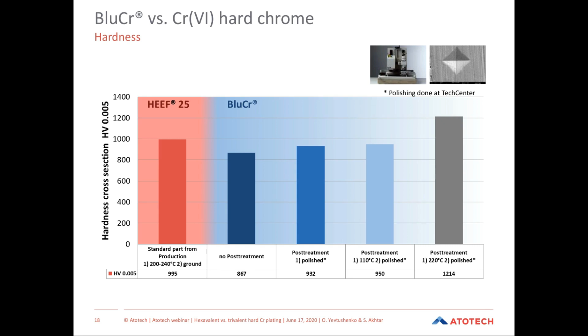However, if you apply post-treatment, like heat treatment and grinding or polishing, then by doing that, you introduce certain heat into the layer. And because there is some carbon inside the BluCr layer, from a certain temperature and after a certain time, the chromium carbide phase will be built, and it leads to the layer hardening.